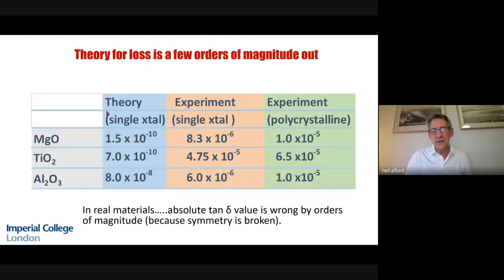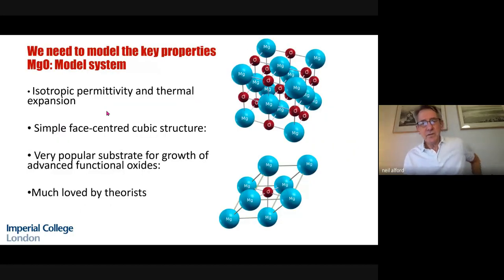What we also find is that this particular theory does not predict the absolute value for the dielectric loss or the tan delta very accurately. And that's because the symmetry is broken. So we need to model the key properties. And what we've done is to use a material, magnesium oxide. This is a good material to use because it's a fairly simple material. It's a simple face-centered cubic structure, and it's a very popular substrate for growth of advanced oxides.